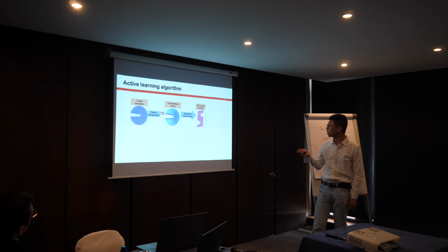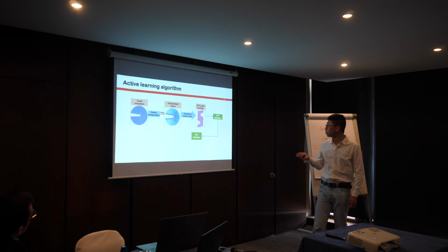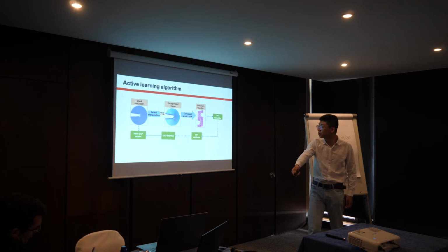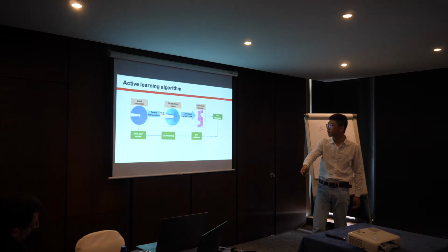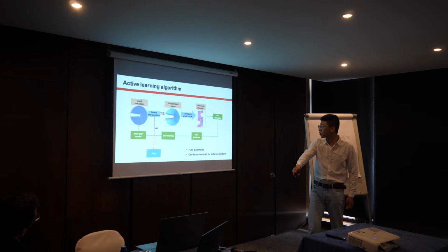This has to be as small as possible and maintain the periodic boundary condition, because DFT is a plane wave calculation, so we need to maintain the periodic boundary condition. We do the DFT on this small crack configuration and add the data back to the database, retrain the model, and repeat this process until there's no extrapolation detected. And this is the automated algorithm.